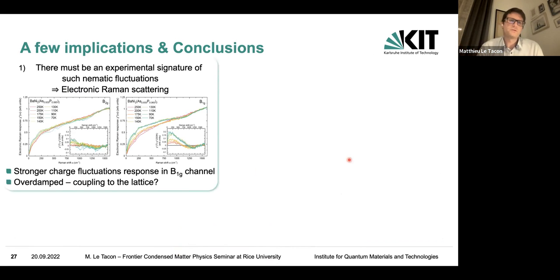Now, it has also a few implications, and the first one is that, well, if you do have some kind of nematic fluctuations, they should be visible with electronic Raman scattering, and because we said that those were most likely to occur in B1G rather than in B2G, well, with Raman scattering, you have selection rules, and you can measure the electronic Raman response in the B2G channel and in the B1G channel. And as a matter of fact, there is a very weak temperature dependence in the B2G channel as you cool down, and quite a clear enhancement of the electronic response at low frequency in the B1G channel. That being said, the response is extremely broad, okay? So it seems to be strongly overdamped, which suggests indeed that this electronic response strongly couples to something, very likely the lattice. But at least it has the right symmetry to couple with the EG phonon, so this was good news.